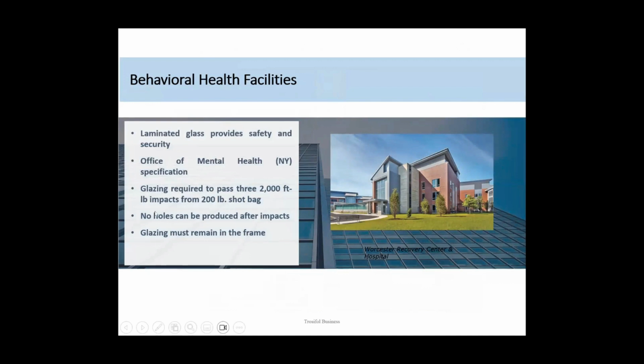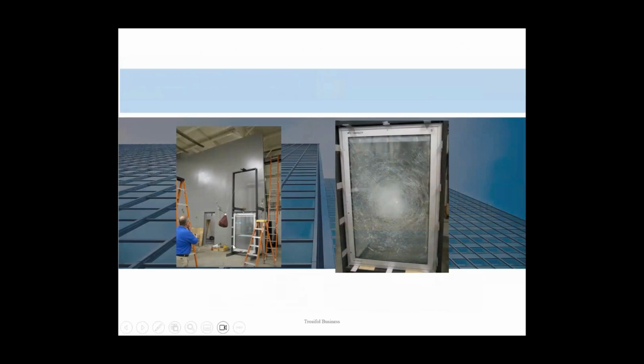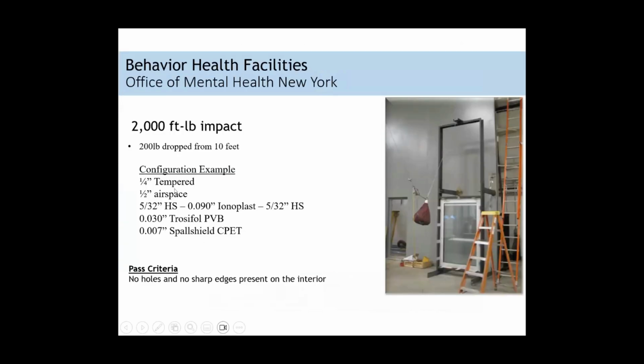All right, so next I want to jump to behavioral health. It's very popular. We've done a lot of testing with our interlayers to the State of New York standards: three 2,000 foot-pound impacts from a 200-pound shot bag. Here's a picture showing what the test looks like and what the glass looks like when you're done. This is our glass solution in order to pass the test. We actually use a product called Spall Shield CPET on the inside of the building that includes PVB and a hard-coated PET. Just in case someone tries to break through the glass with their hands, the Spall Shield CPET will prevent the hands from contacting the glass. So it's a much safer solution.